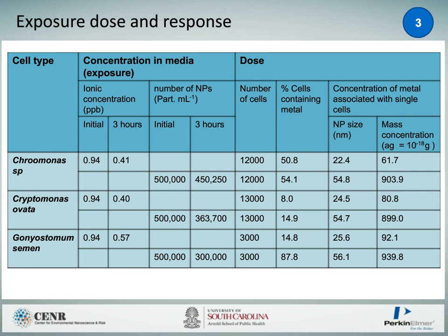So the kind of interesting stuff we can get from this is just a table to show an overview of the results that we got. So I've shown that you can look at the exposure, which is the part on the left-hand side. We added an initial concentration that was measured in all samples to be around 0.94 ppb of gold. And you can see after 3 hours that we lost anywhere between 40 and 60% of the initial added amount of ionic material. And you can see the same with the particle number concentration. We added around 500,000 particles per mil, and you can see that after 3 hours, different amounts of these particles have been lost to the system.